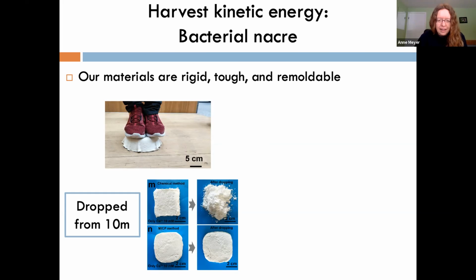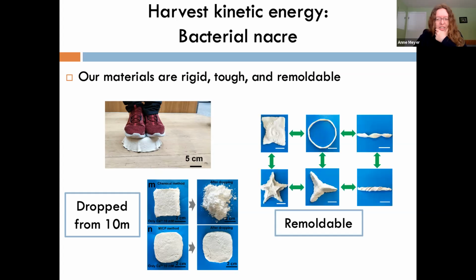You can see that on the top, that's when you only have the calcium carbonate. Calcium carbonate by itself is very brittle, so it just explodes into powder. And on the bottom, that's when we had the full thing, the cellulose mineralized with the bacteria, and we don't see any visible changes after dropping from 10 meters. So it's very robust and resistant to fracture.